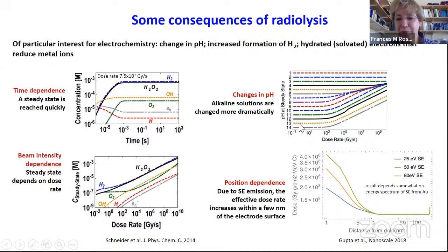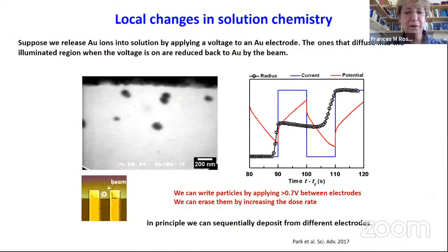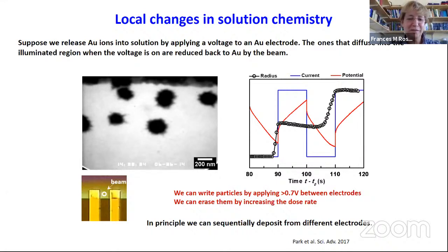But if you start with something that's alkaline and you go to the dose rates that we use in the microscope, something that started out at pH 14 is going to end up at pH 10 or 11. So dramatic changes could happen just at the moment your beam goes on the sample. Okay, so here's an example of one of these experiments.